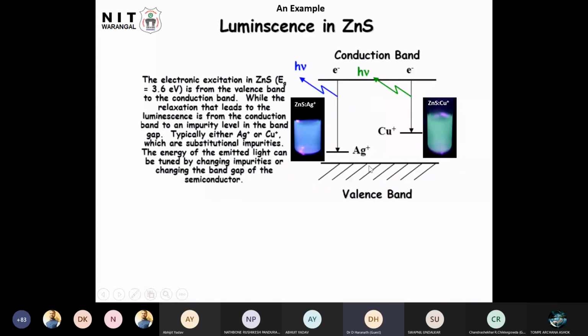So if I dope zinc sulfide with silver, I get blue emission. Blue, zinc sulfide silver is blue. But instead of silver, if I put copper, I'll get red, green, very good green. Similarly, if I don't use copper or silver and use manganese, same zinc sulfide, earlier I have shown that it gives red color. That means the host is same, but if you can play with the activators, you can get whatever color you want out of all the visible light. So that is the beauty.